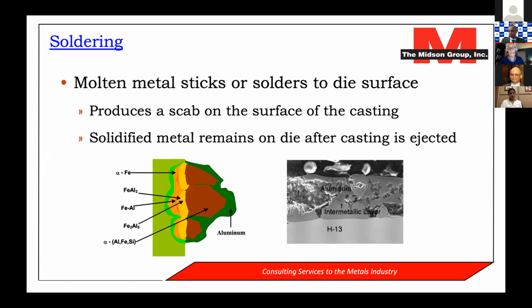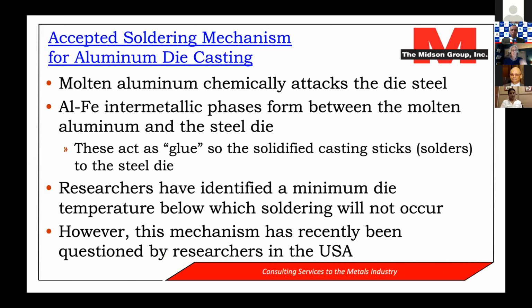Soldering, again, most die casters, I'm sure, are very familiar with. This is when the molten metal sticks or solders to the die surface and produces a scab on the surface of the casting once we eject the casting, and then a small amount of the solidified aluminum remains on the die after the casting is ejected.